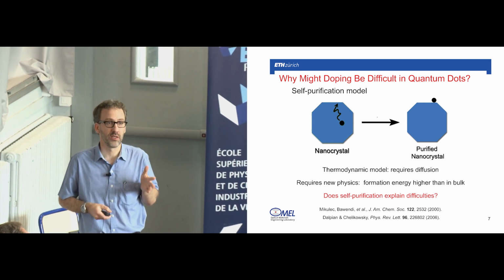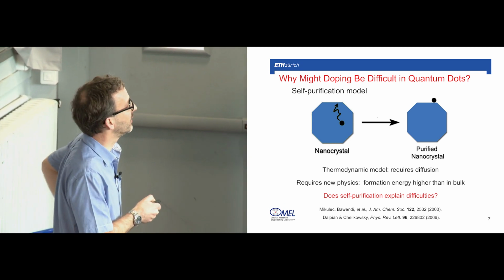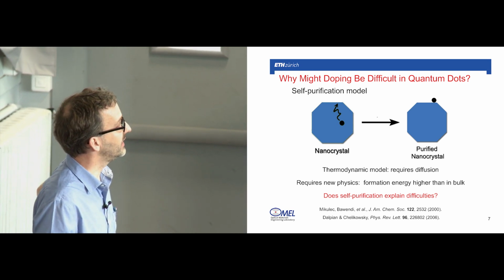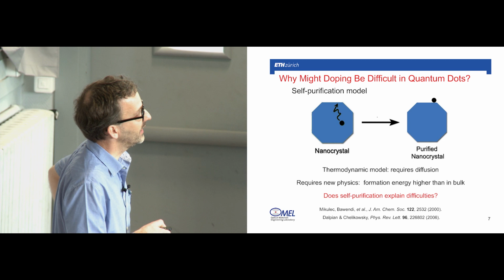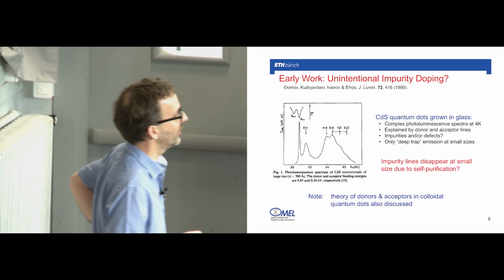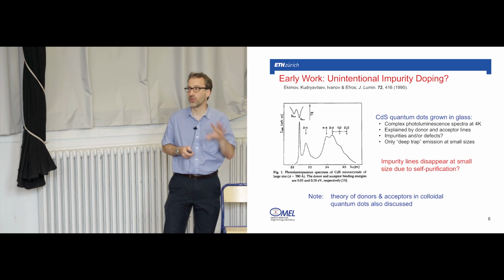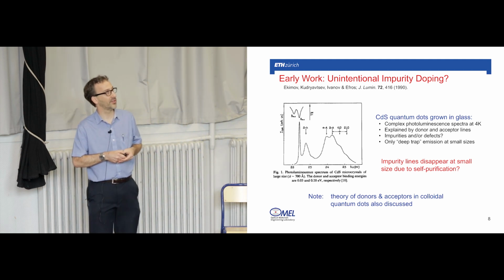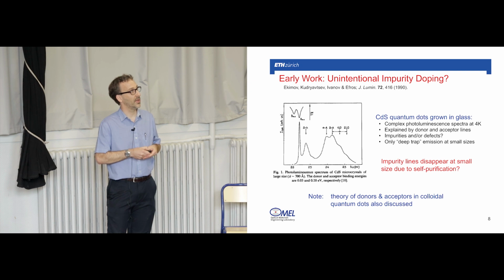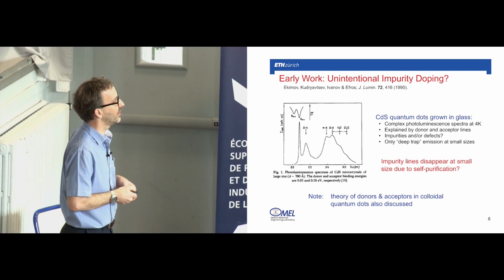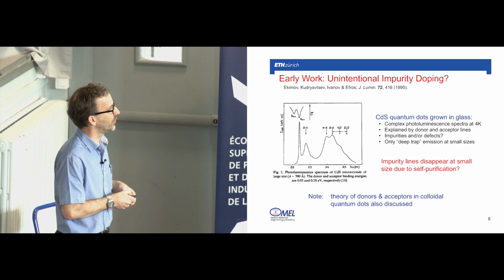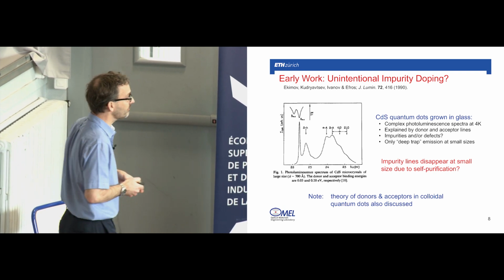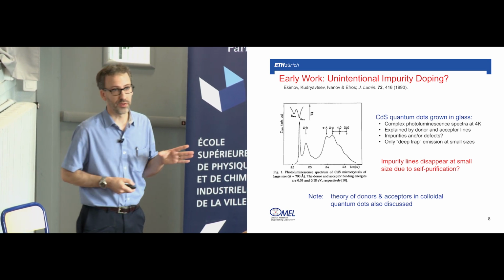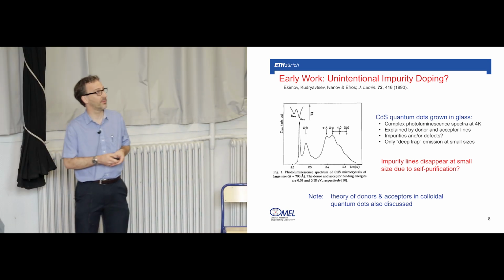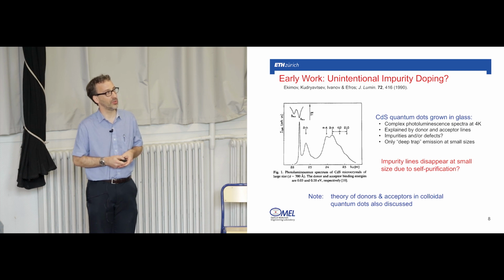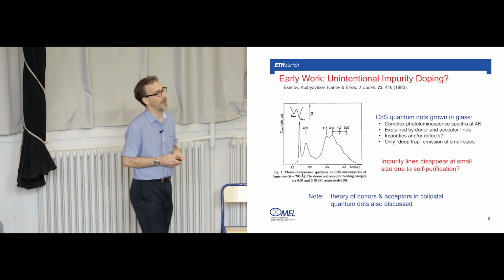One paper I'd like to point out, I think it's a really underappreciated paper, by Alosha and Sasha in 1990, where Alosha had made cadmium sulfide quantum dots in glass, as we've heard about. At low temperature, when the particles were large, they saw very complex photoluminescence spectra. So they had the band edge peak, and then they had all these other lines, and they assigned those to donor and acceptor transitions. As far as I understand, it's still not known where these lines come from, but they speculated in this paper that they're due to impurities and or defects.